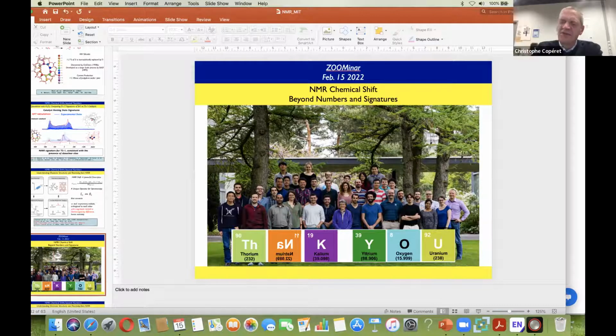I think people have tried to measure that in solution, and no one has ever seen any barrier. What people have seen is actually a very low JCH coupling constant. So the JCH coupling constant can go down to 90 Hertz, which tells you that you have a very much elongation of the CH bond. But so far, as far as I know, no one has been able to identify a barrier for this system, which is not true in the case of beta H agostic. You actually see some barrier of rotation.